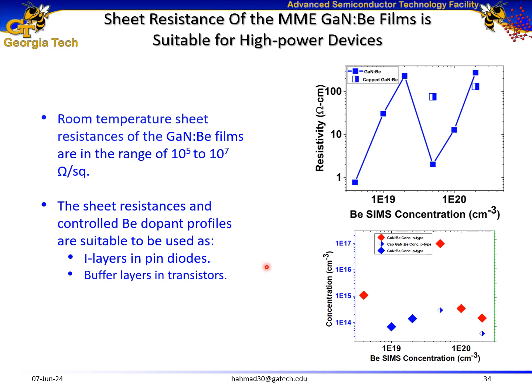Then I grew several samples of beryllium-doped gallium nitride in the beryllium doping range of mid 10 to the power of 18 to low 10 to the power of 20 per centimeter cube. And I achieved sheet resistances in the range of 10 to the power of 5 to 10 to the power of 7 ohm per square, which are suitable to be used as I layers in pin diodes and also as buffer layers in transistors. The carrier concentrations of these films were in the range of 10 to the power of 14 to 10 to the power of 15 per centimeter cube, suitable for I layers in pin diodes.